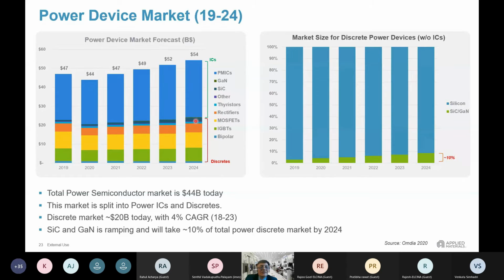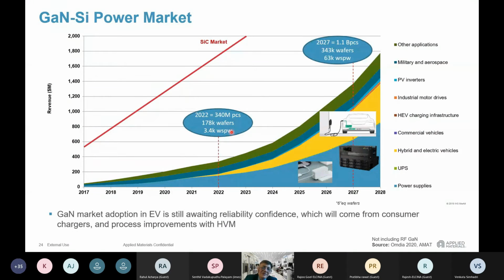And if you take this at 10% of this entire thing, you are talking of close to about $4 billion, which is now the projected demand for GaN and silicon carbide by 2024, 2025. So it's actually a market which is very, very interesting from the investor point of view. It is this market where devices were constrained that impacted the auto segment. Okay, but that has a separate story.